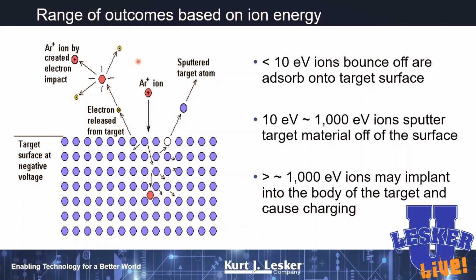Now, just a little more detail here. Here's our argon ion that we created with collisions of the electrons we generated and our argon atoms. This argon ion is going to crash into the surface of the target, and based on the energy that it has, and we have some control over that energy by how much we bias the target itself, if everything goes well, that ion is going to crash into the surface of the target and eject a sputter target atom or molecule, which is going to go up there and become part of our coating. Based on the amount of energy, if we don't have a lot of energy as this ion crashes into the target, it may simply bounce off the surface and we won't get any sputtering. If the energy of that ion is, let's say, under 1,000 eV, that ion is likely to do its job, crash into the target, and physically knock a sputter target atom out.